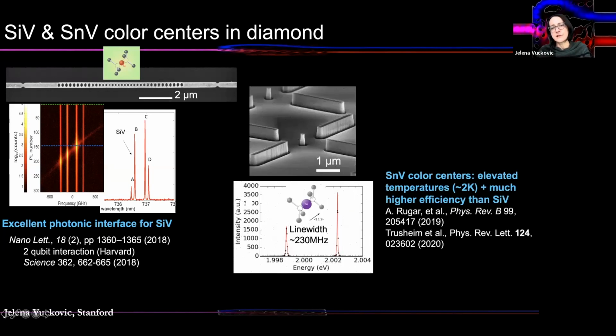And also more recently, there has been a lot of activity on tin vacancy color centers in diamond, which promise all the benefits of silicon vacancies with operation at slightly elevated temperatures. And slightly elevated temperatures here means few Kelvin as opposed to millikelvin, which is unfortunately needed for silicon vacancies to obtain the best results. And also tin vacancies have higher internal quantum efficiencies than silicon vacancies. So that's also favorable because you basically work with the brighter quantum emitter and you have more scalable system. These results that I'm showing here are from my group's work for tin vacancy. At the same time, when we did the spectroscopy, there was a work done in parallel in the group of Mete Atature at Cambridge and Dirk Englund at MIT, confirming also agreement with theory.